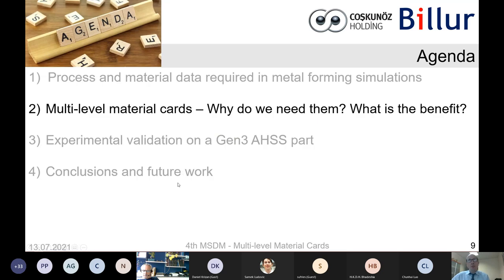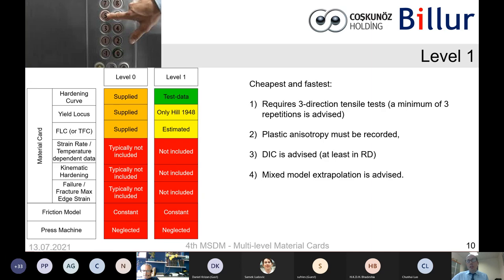So that brings us to our multi-level material cards. What we discussed in the initial idea is that let's have several levels or blocks of tests that we will do for sheet metal forming simulation. And level one would be the cheapest and fastest. What we do is only three-directional tensile tests. We must record the plastic anisotropy with respect to